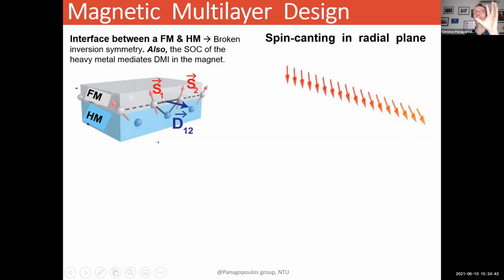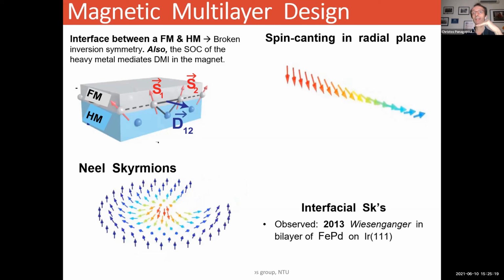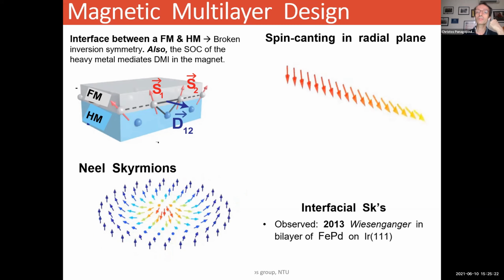So remember, at this stage, I'm not working with my superconductor at all. I am trying to figure out how to design the right magnetic multilayer in order to deposit on it my superconductor. And this magnetic multilayer needs to have the right ingredients in order to stabilize skyrmions that are of the right size that would make sense for coupling to the vortices. So having this interfacial or multilayer magnet would give me the right spin canting in the radial plane, but in 2 dimensions, this canting would give rise to so-called Néel skyrmions.